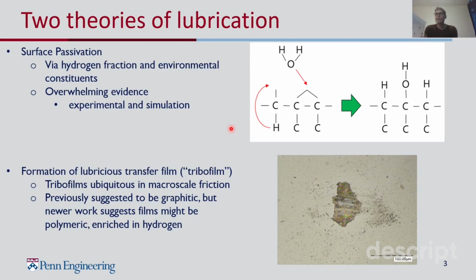And it's been known empirically for probably 30 years that this is really important in achieving low friction. If you don't have the tribofilm in a lot of DLC systems, you won't have low friction. And so researchers have tried to figure out how they work for a long time. A lot of the early research suggested they might be graphitic in nature. So the low friction mechanism is just graphite sheet sliding against a graphite sheet.